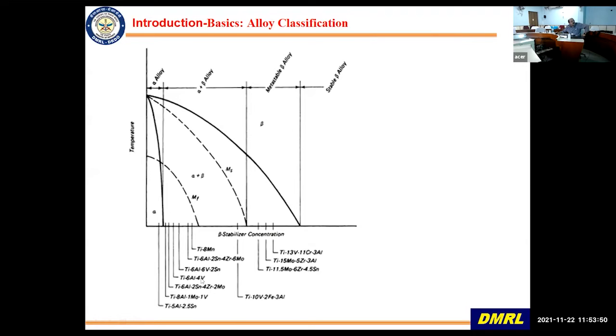One of the important alloys that I should point out is Ti-6Al-4V, which is an alpha beta alloy, and around 50% of the world's titanium production is of this alloy, because this is a medium temperature capable, good strength alloy, and it is used widely in many places. Then you have the metastable beta alloy, Ti-10V-2Fe-3Al. Then you have other alloys also.